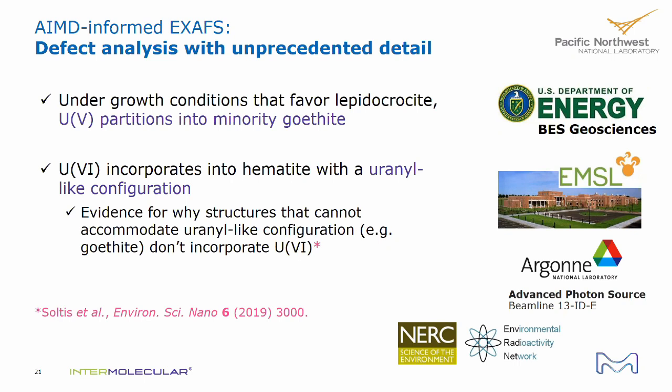So we'd have a different supercell with a different coordination structure and different dynamics. And from each individual supercell, we'll calculate an XAS spectrum. From supercell to supercell, as you have different coordination structures on the uranium, then yes, you would expect a different, or potentially a different, delta E naught.